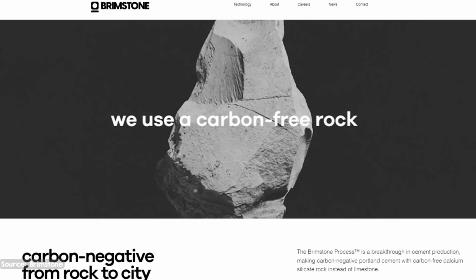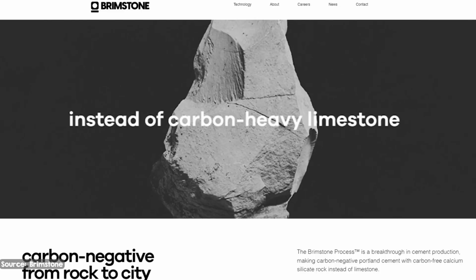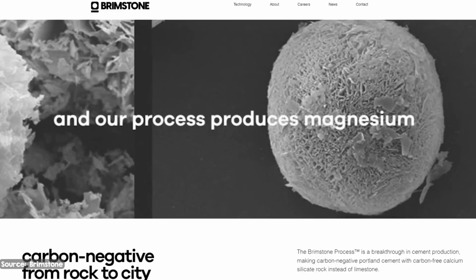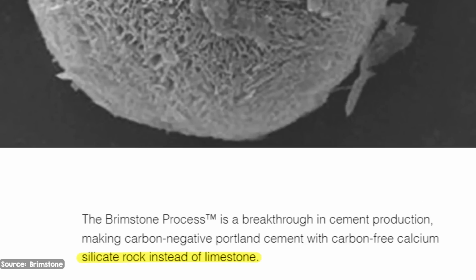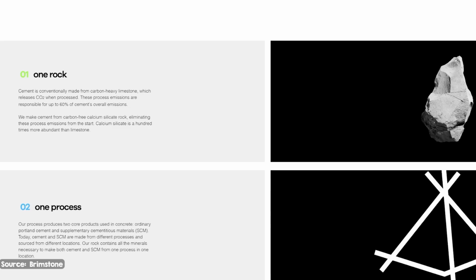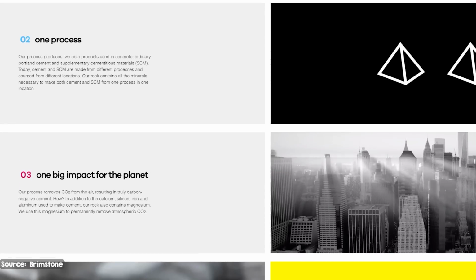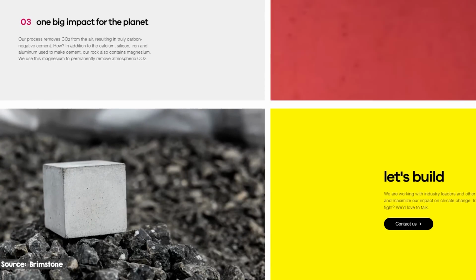Now, using less cement and less clinker in that cement will help to reduce the amount of CO2 released from turning limestone into lime. But what if we were able to avoid that process altogether? Limestone is the most common type of rock used in cement manufacturing, but it's not the only one that can be used. A US startup called Brimstone has developed a method that they claim produces no process emissions, creating cement from calcium silicate rock. The final product is chemically identical to Portland cement, but because there's no carbon in the source mineral, there's no CO2 produced.